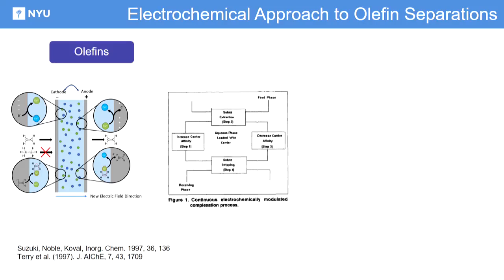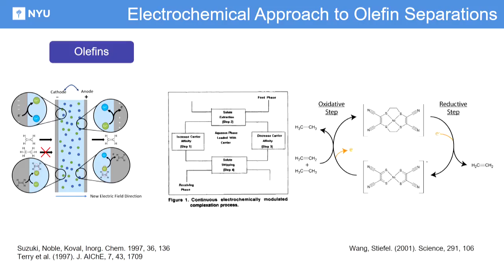gases. There's, of course, a lot of transport issues when it comes to this, because usually when you think about these electrochemical cells that are run in aqueous electrolyte, the solubility of these gases is quite low, so you really have to think about the reactor design that goes behind operating these at the really high throughputs that you need for production of olefins. Also, copper tends to poison with sulfur, and so does silver, which is another metal. So about 2 decades ago, a group at Exxon discovered this set of molecules, nickel dithiolenes, which can very selectively bind olefins. So I think there's big opportunities for organometallic chemists to design systems that can change reversibly their affinity towards olefin versus paraffins, and then develop in this way these electrochemical swing absorption systems.